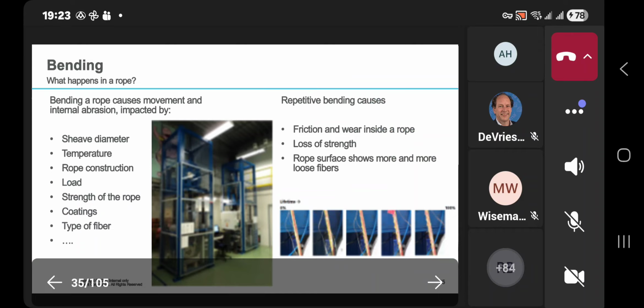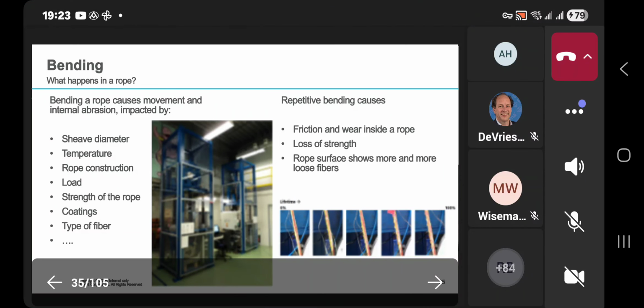So what actually happens when bending such a rope repetitively over a sheave is that you will create some internal friction, and that is caused by abrasion inside the rope. And this will lead to a decrease in strength, which can be observed by an increased number of loose filaments on the surface of the rope, which finally leads to breakage.